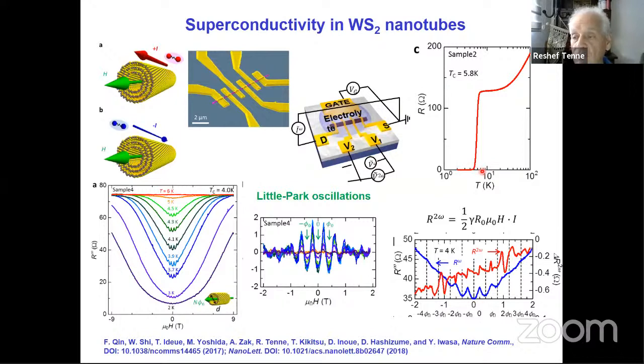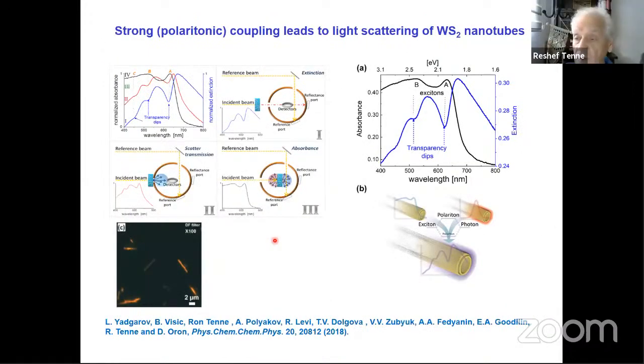The way that you can judge that this is 1D superconductivity, I won't go to the details, is the Little-Parks oscillation. The Cooper pairs simply interfere with each other and form an interference pattern, and therefore they can circulate in phase in the nanotube, and they form these oscillations which come very close to the critical temperature, but not above that. So this is one demonstration of the 1D nature. The other nature, there are several papers now that we have published, and others, on the properties.